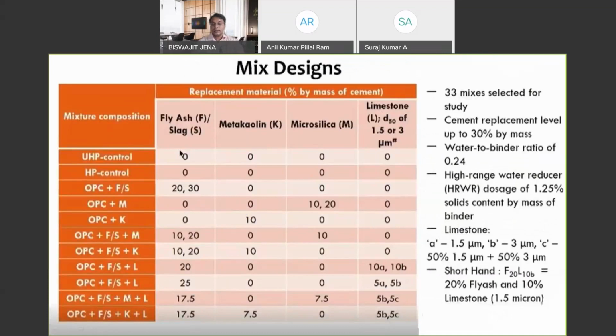So next, with the available materials, we designed a large number of systems of paste mixes. Actually, for the study purpose, we have taken 33 mixes, having a very low water binder ratio of 0.24. Theoretically we have taken 0.24, but actually even less than 0.24. That is 1.25% of high range water reducing admixture, which is a polycarboxylate based water reducing admixture, 1.25% solid by mass of binder, which actually translates to about 5% of superplasticizer by mass of cement. I will show you how to add that also, the designing part.